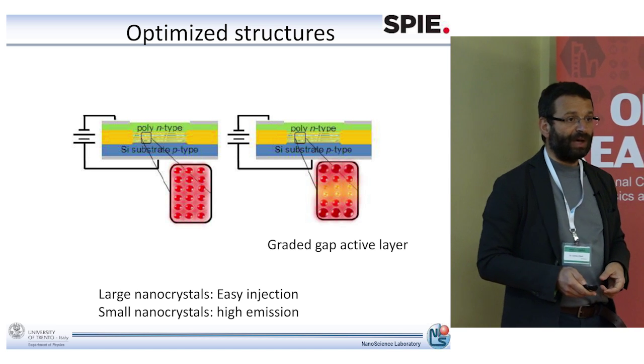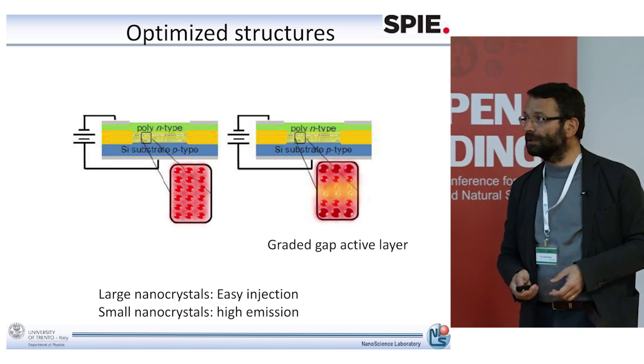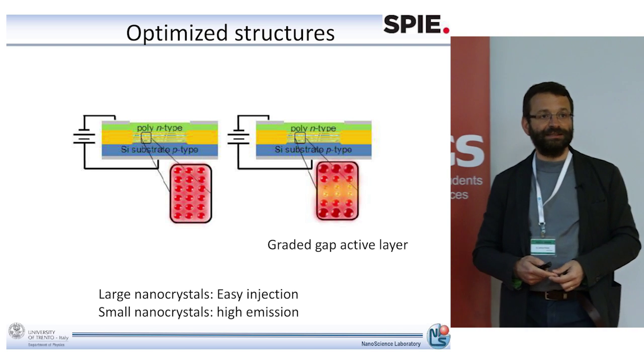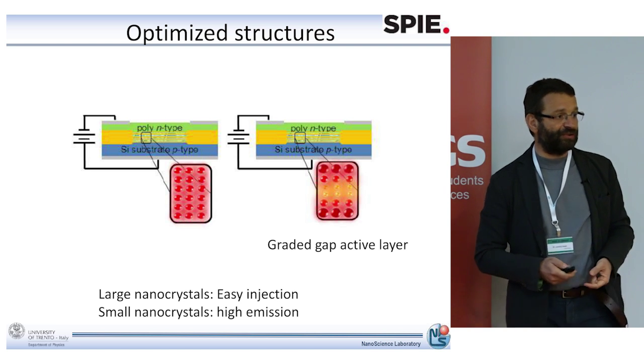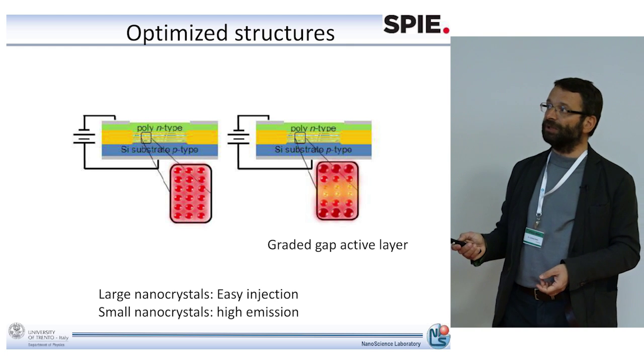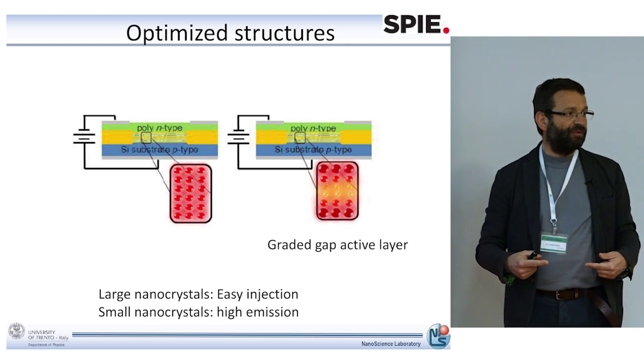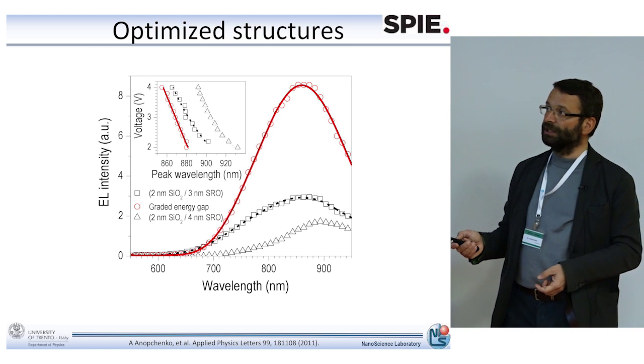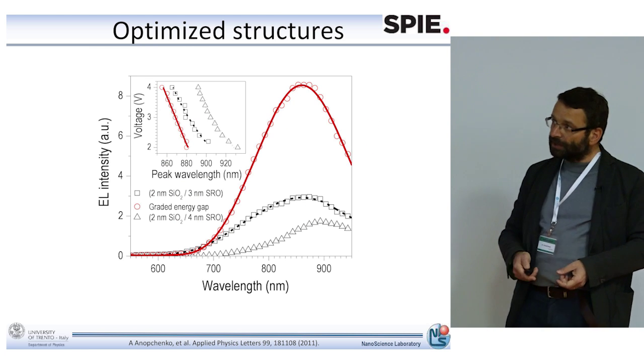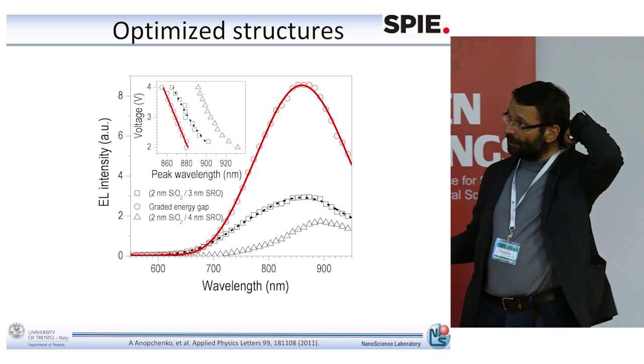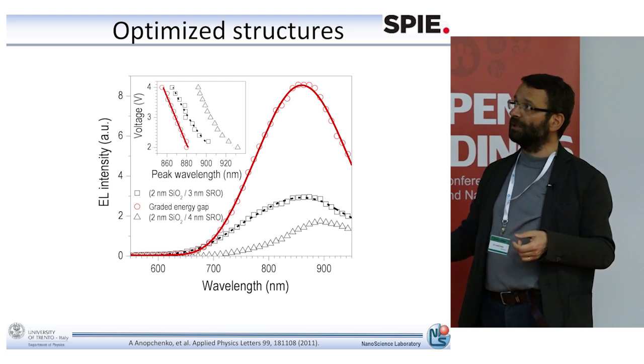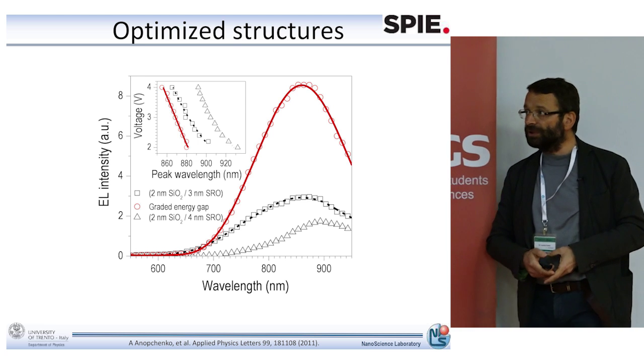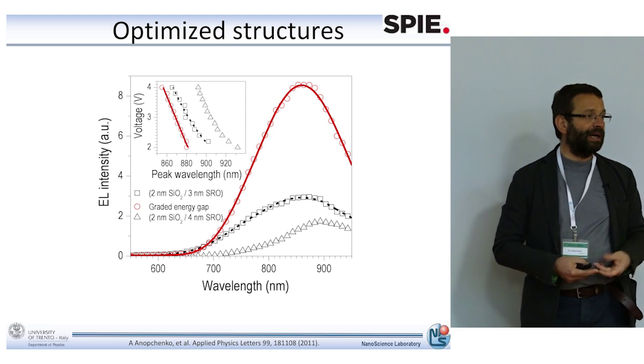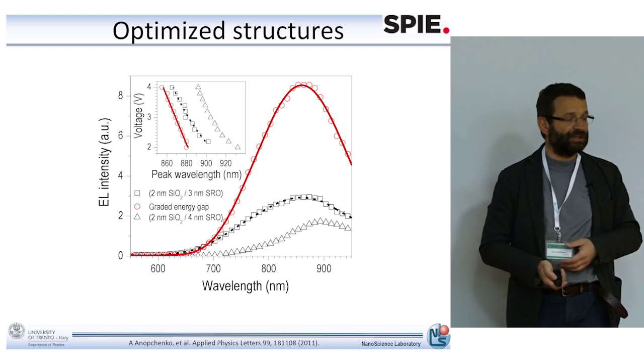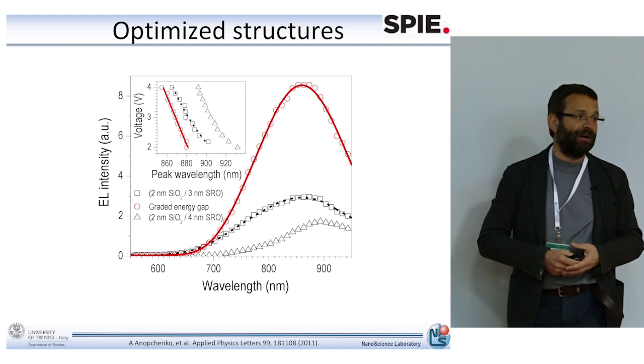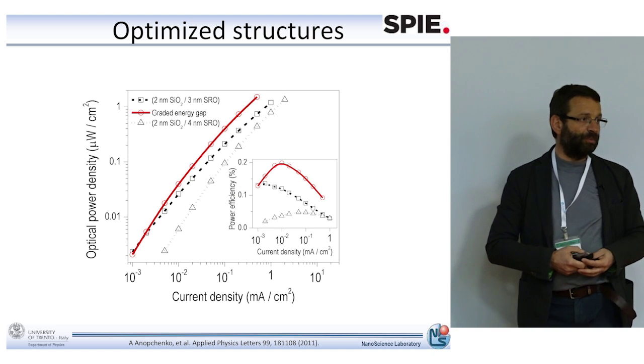That's good. Are we happy? Unfortunately not. Because now if we convert the electroluminescence intensity into a power efficiency, what we see here is that the power efficiency, despite our effort, is still lower than 1%. In this example, it's 0.2. So here is a silicon nanocrystal LED, a few thousand of them on a CMOS wafer. We turn on the light, and we get some visible light, orange, perfect, coming from the nanocrystal. However, unfortunately, the power efficiency is low, 0.2%.